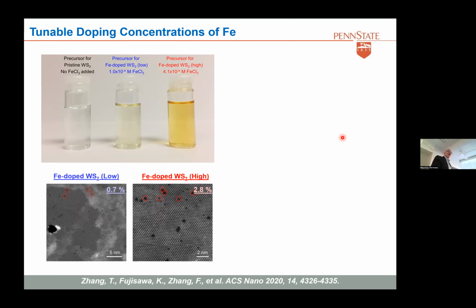We're also trying with iron. This is just the way the system works. You can see the precursor of tungsten when there's no iron chloride. When you put a little bit of iron chloride, you get the suspension. This is the one that you spin coat. And when you put more concentration, you can see a more yellowish color. This is the one you spin coat, you do your reaction, and you have iron doped at 0.7% or highly, at 2.8%. Vanadium is very particular because you can put it all the way to 12%.